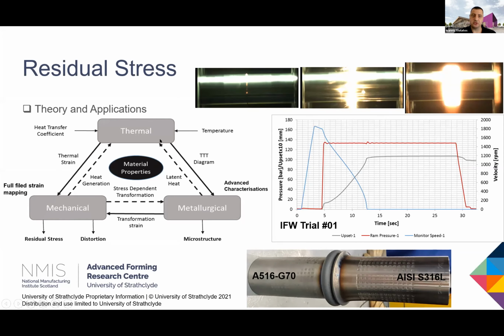And all of these factors contribute to what we see. In these specific cases, and I think you have taken note in the previous trials, the stainless steel is obviously stronger at elevated temperature. That is why it deforms less than the 516 steel, and that actually means that we expect completely different stress profiles in these two materials.